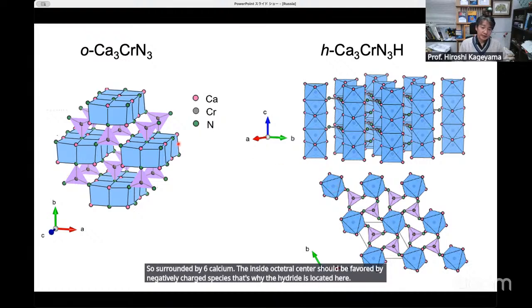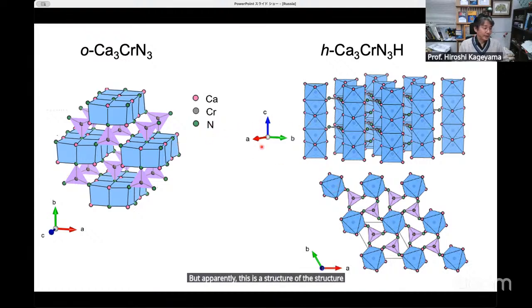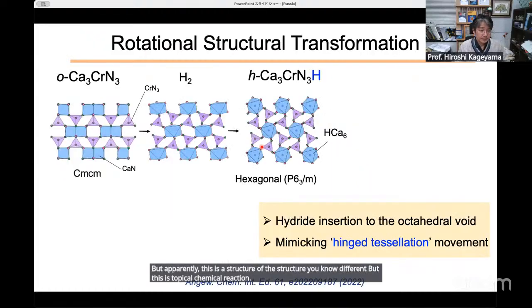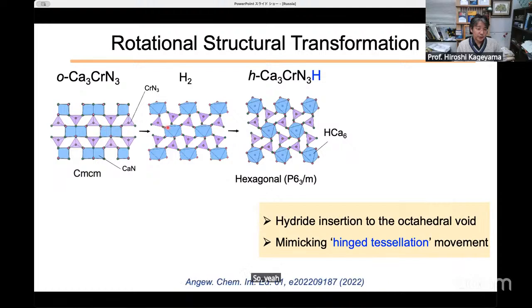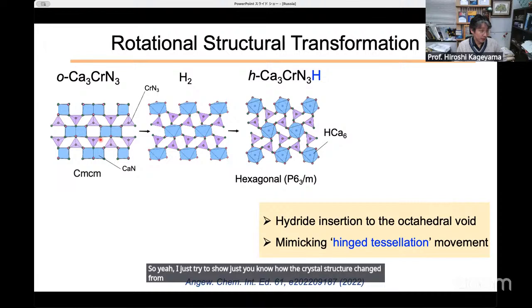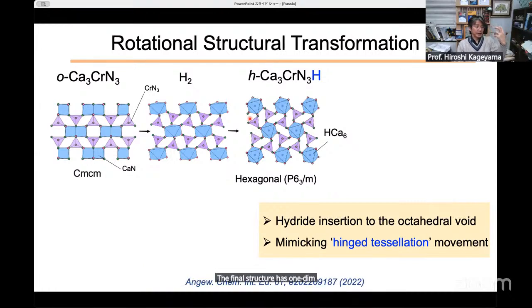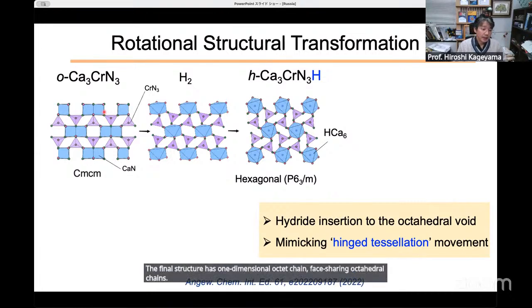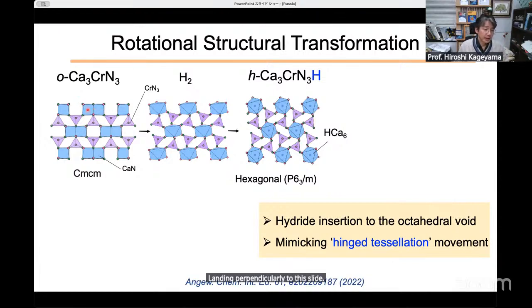But apparently, this crystal structure is very different. Okay, but this is a topochemical reaction. So here I just try to show how the crystal structure changed from the orthorhombic structure to this hexagonal structure. The final structure has one-dimensional octahedral chains, with face sharing of octahedra. But the starting structure has one-dimensional blocks running perpendicular to the slide.